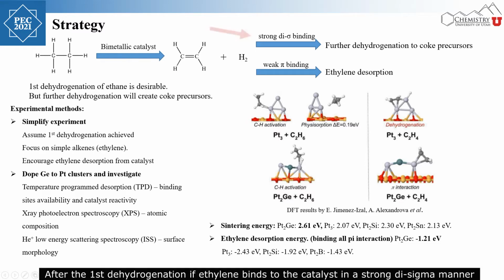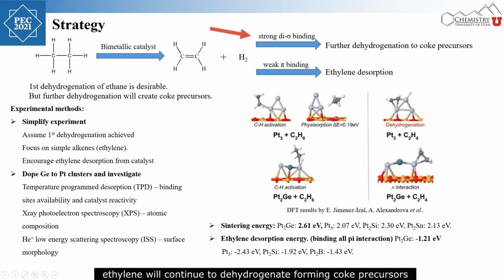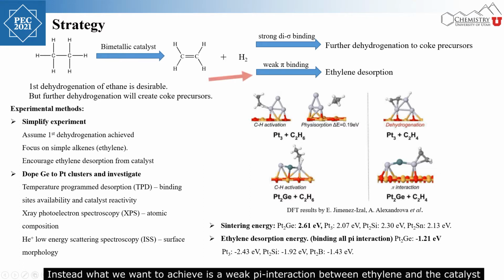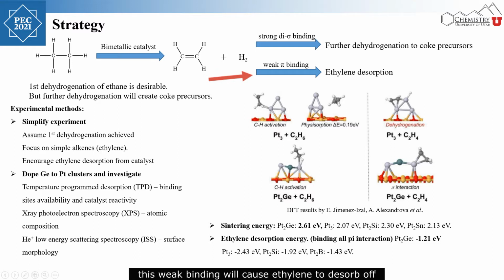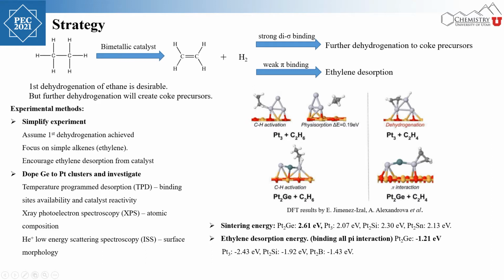After the first dehydrogenation, if ethylene binds to the catalyst in a strong di-sigma manner, ethylene will continue to dehydrogenate, forming coke precursors. We would like to avoid this from happening. Instead, what we want to achieve is a weak pi interaction between the ethylene and the catalyst. This weak binding will cause ethylene to desorb, thus preventing coke formation.